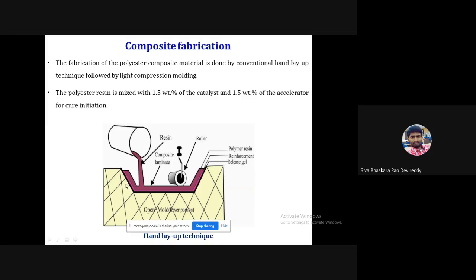Initially, the resin is applied over the mold and the glass fiber mat is placed in such a way that we get a 4 mm thickness. In this way we fabricated this composite.